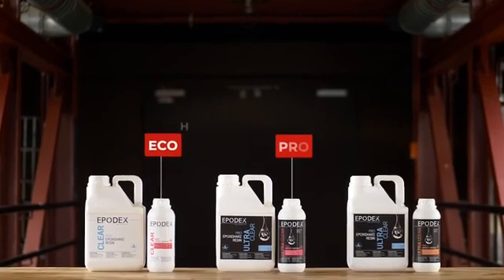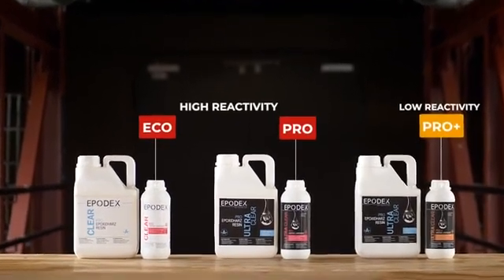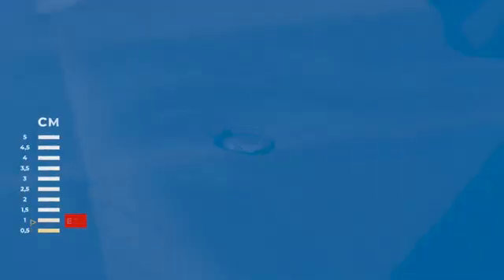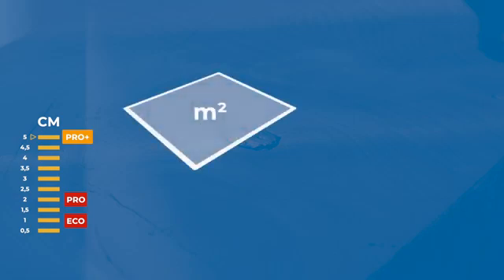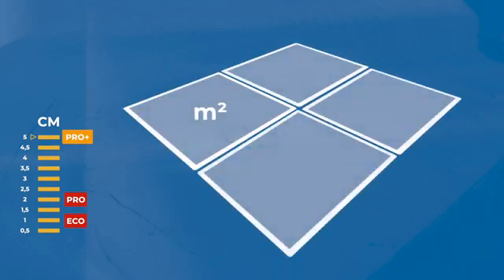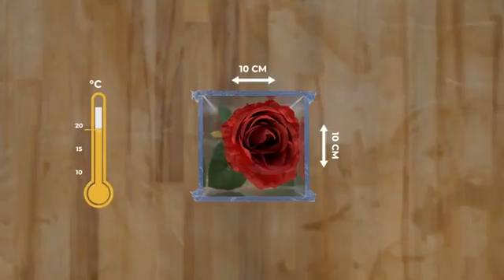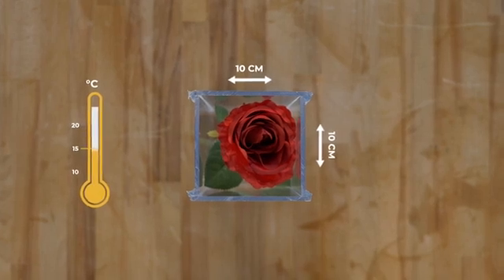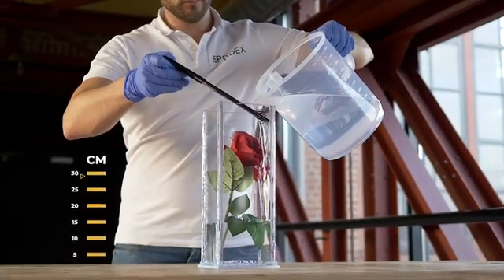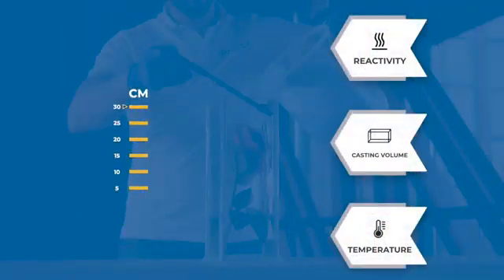Epodex's Eco and Pro system are more reactive than the Pro Plus system. While you can pour up to 1 cm with the Eco system and 2 cm with the Pro system, the Pro Plus system can be poured up to 5 cm thick in one pour. For all three systems, the maximum thickness applies regardless of the size of your project, at room temperature of approximately 20 degrees Celsius. If you pour small areas or lower the room temperature, you can cast with our Pro Plus system up to 30 cm thick at once. The maximum pouring height is not only determined by the system's reactivity, but also by the area to pour and the temperature.